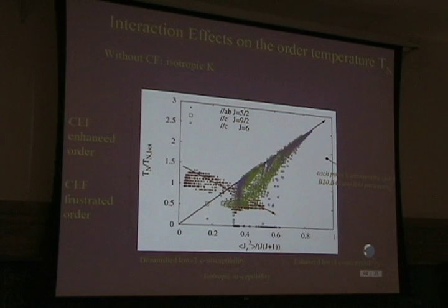The energy splitting, we saw that they are the same, they shouldn't matter. But we found a very systematic evolution of that wave function of the ground state. So let's see if changing only that wave function, and the likeliness of being along the z-axis to have a g along the z-axis much bigger than in the plane, can change T_N.